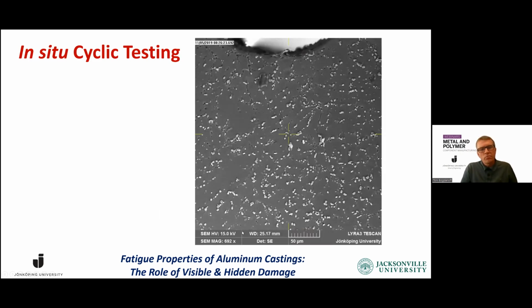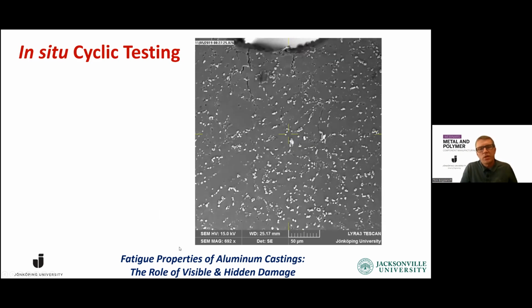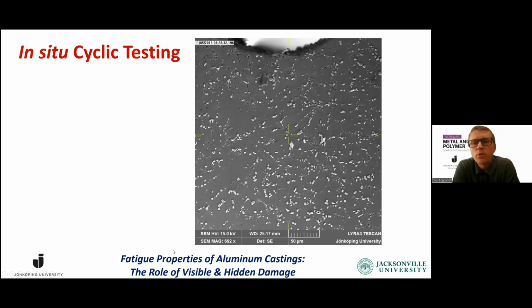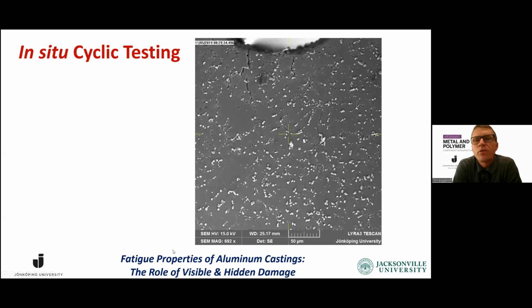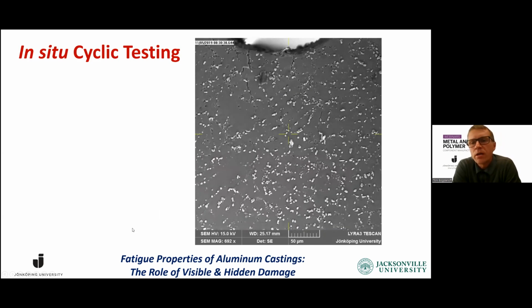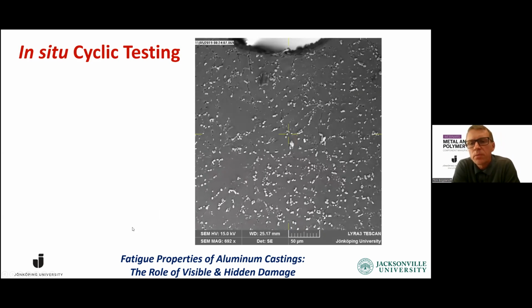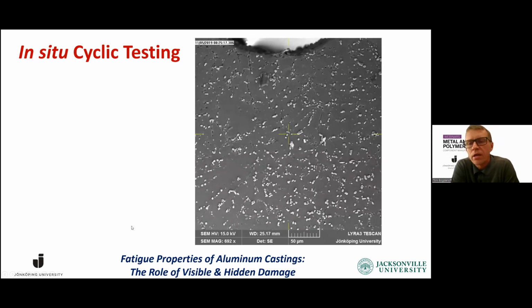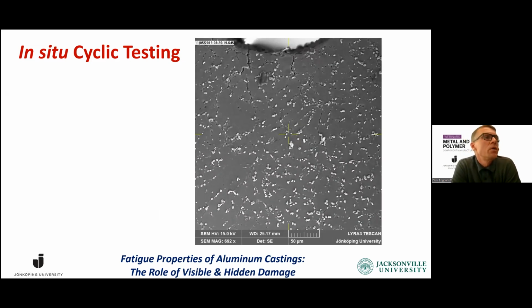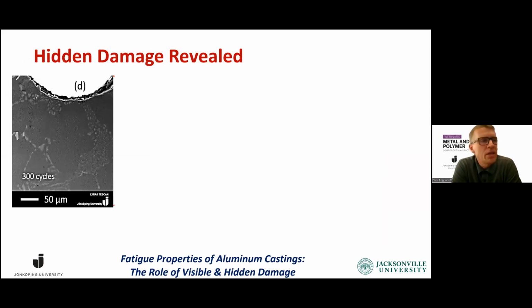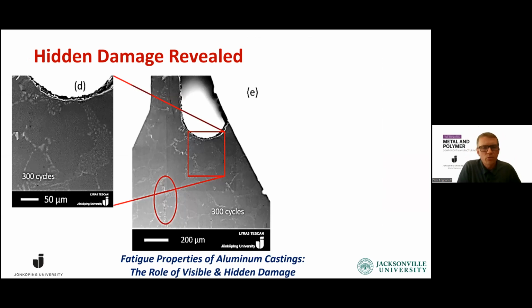So we can also take a video of this, so we can actually see it afterwards. To the left of the notch, we see that this is the main crack, but we also see a lot of other cracks opening up. That one I will discuss more in the next case that we will discuss. But in this sample that was HIPed, we did the cyclic testing, and we saw after 300 cycles, we didn't see anything close to the notch where the strain concentration should be highest. But far away from the notch, we see things opening up in the material.